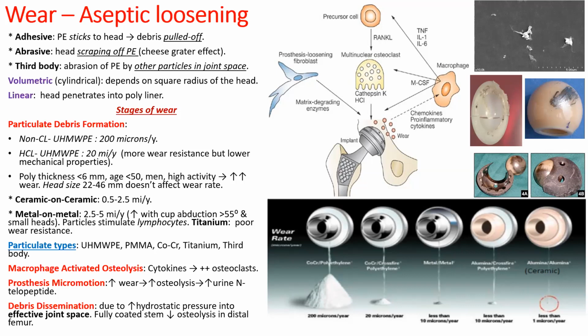These particulate debris will initiate inflammation mediated by the macrophages through inflammatory cytokines, and this causes stimulation of the osteoclasts, and the stimulation of the osteoclasts causes osteolysis. The osteolysis increases the potential or the reactive joint space and causes the particles to spread in more than the initial areas where they started, and also increases the reactive fluid that's formed, which increases the hydrostatic pressure, and there will be a vicious circle of spreading of the particles in the joint.